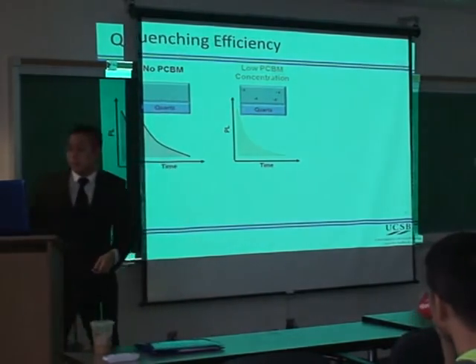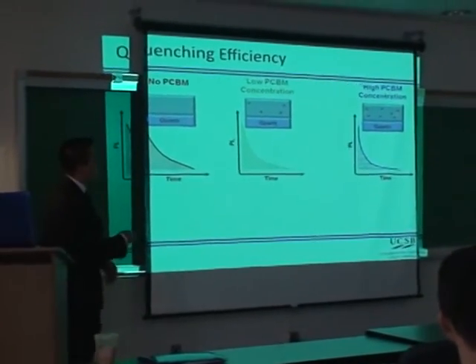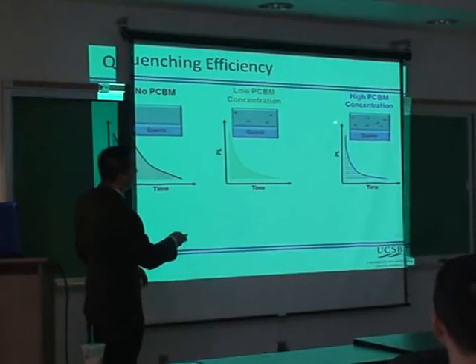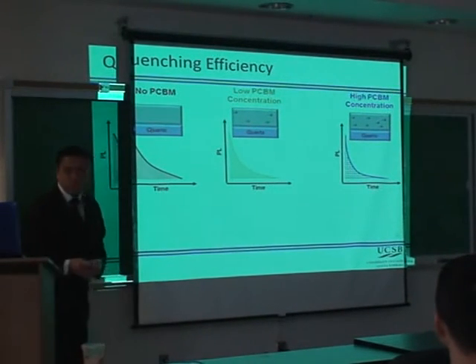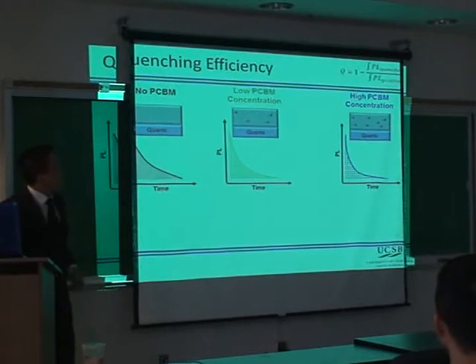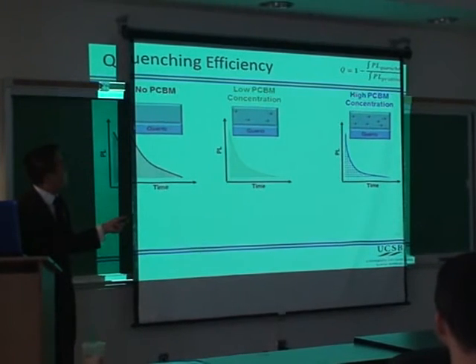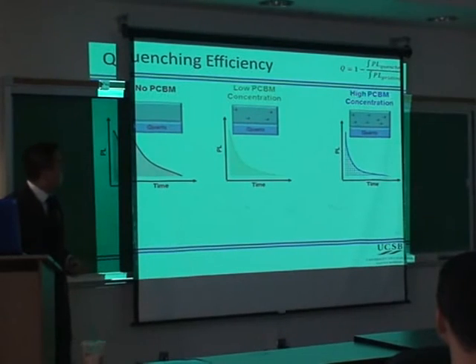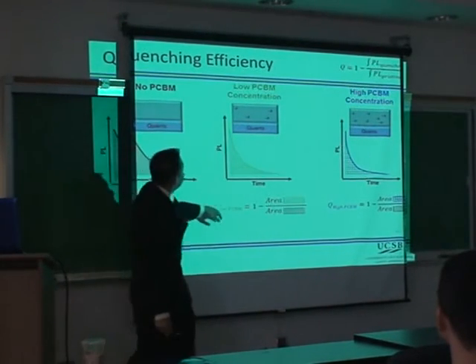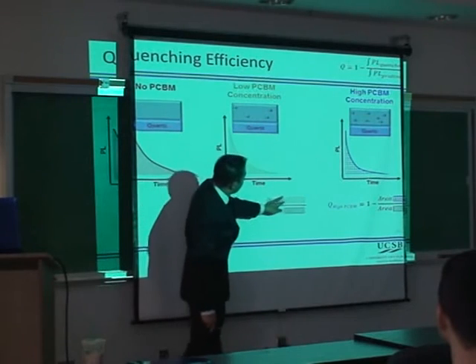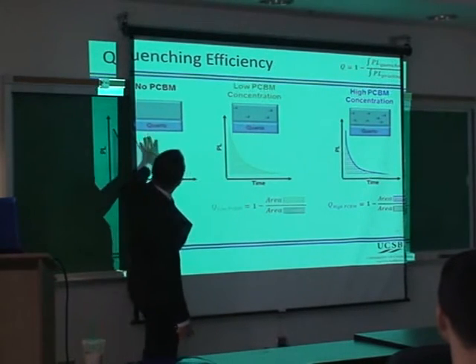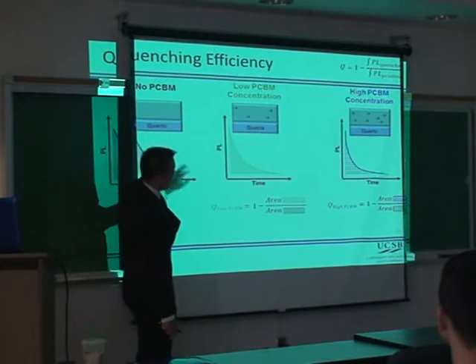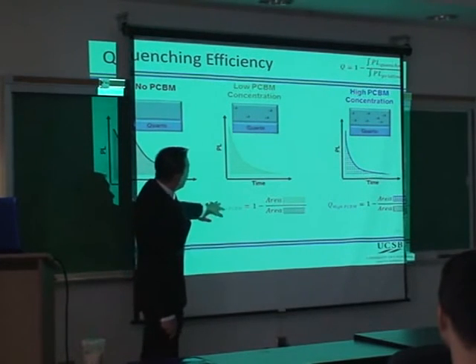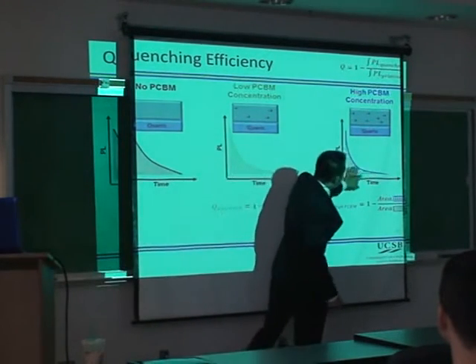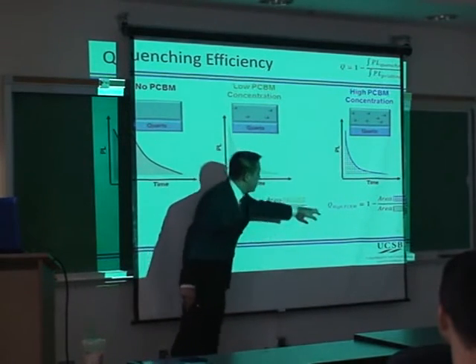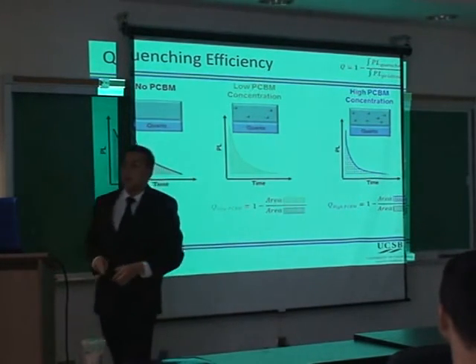And to exaggerate that a little bit further, we could show that if we further increase the PCBM concentration, the lifetime decreases further. So again, using the similar formula as last time, where you have the integrals with the quencher over without quencher, we could calculate what's the quenching efficiency of each of these films. So it's just basically the area with the quencher over the area without. And this is the film without any quencher, the control you can think of. And what you see is that when you have more quencher, you have a higher quenching efficiency compared to when you don't have as much of a quencher.